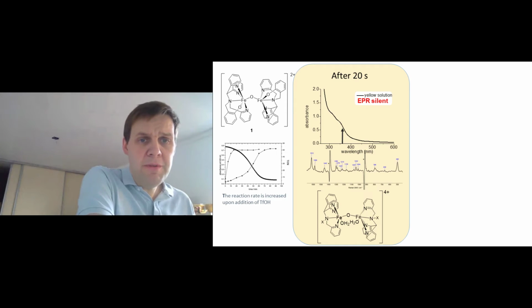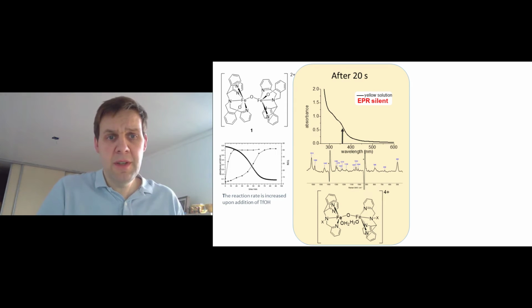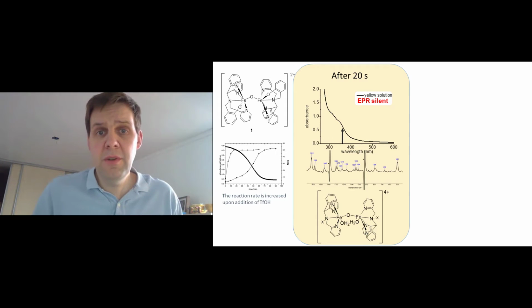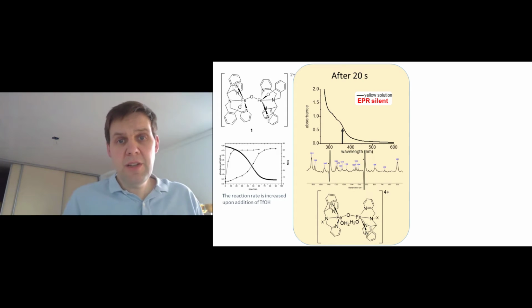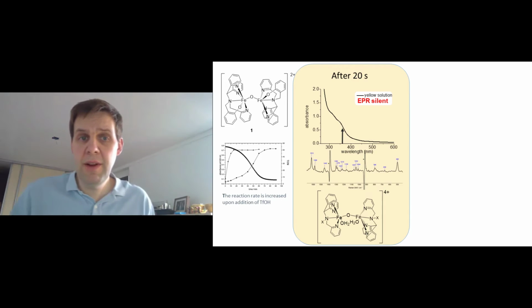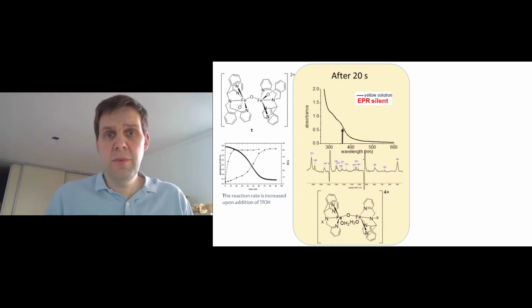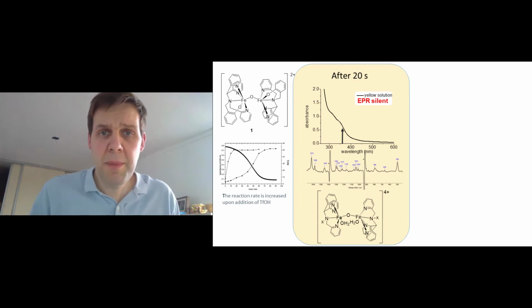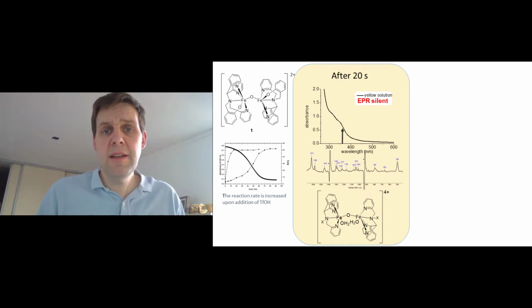And if we look at the profile, well, within the first, let's say, 15 minutes, we see conversion. So our catalyst has undoubtedly changed structure in the first 20 seconds and thereafter does the catalysis. So we have two questions. What is happening in that first 20 seconds? And secondly, what actually is doing the catalysis?